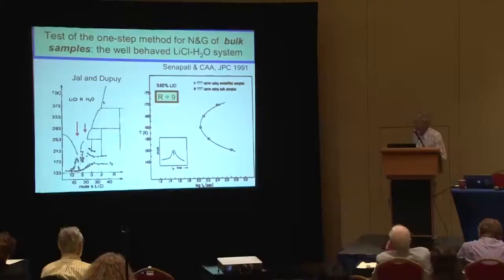And now that was done by emulsifying the solutions, lithium chloride water solutions, in order to protect against heterogeneous nucleation, so that we could sequester most of the dirt in the system, which would provoke nucleation at higher temperatures, into a very tiny fraction of the sample, and then we would see the homogeneous nucleation event uncontaminated by other things.